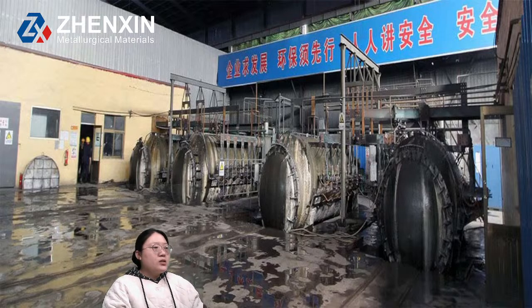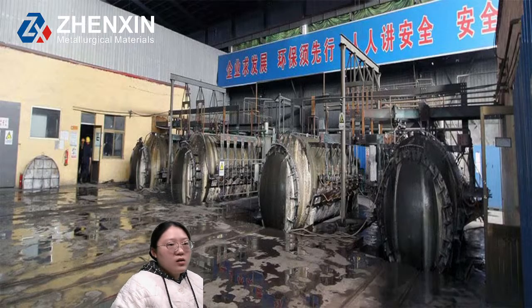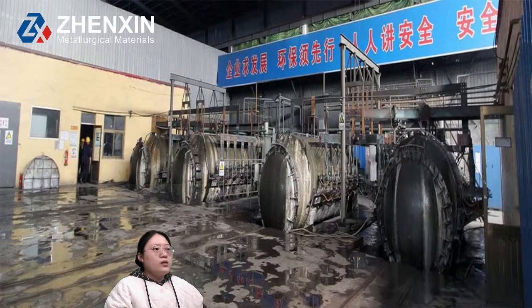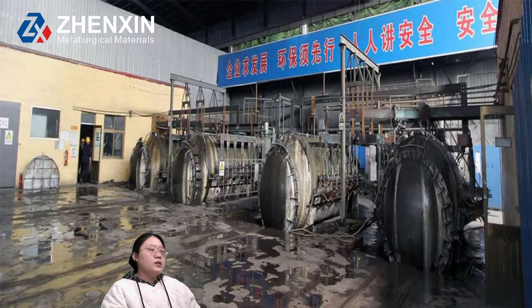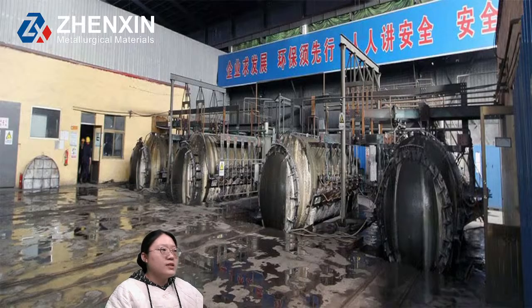The first is over nodulization. If you face failures in your process, over nodulization will make chunky graphite, shrinkage, and poor machinability. Yes, over nodulization will make chunky graphite, shrinkage, and poor machinability.